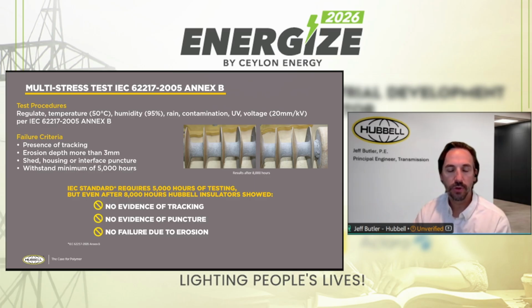Similar failure criteria were evaluated for tracking and for crazing, with an erosion depth of 3 millimeters. Unlike the previous test, where we did it on just plaques of rubber, this was done on actual sections of insulator. So you could evaluate the breakdown or degradation of the rubber that could expose the fiberglass rod. The threshold was set for us to a minimum of 5,000 hours. The test per the standard does define 5,000 hours, but we actually increased that and ran the test for 8,000 hours. The photos shown there are the insulators after 8,000 hours. So that's 60% more exposure in the test, and yet we still successfully passed the test.